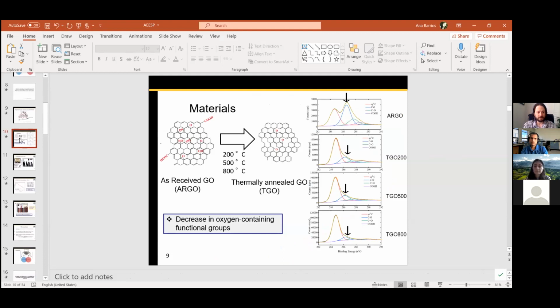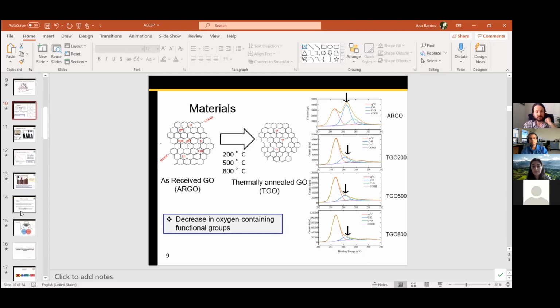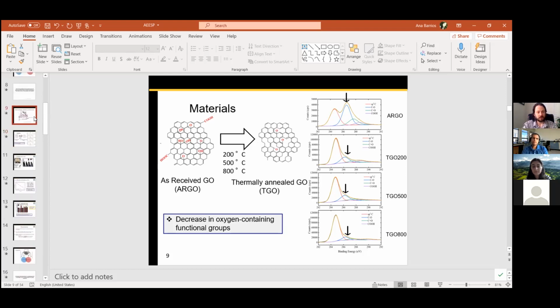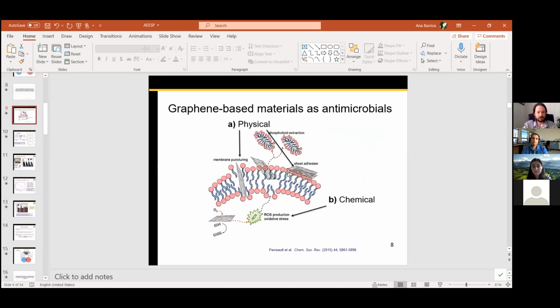The thermal annealing just basically helps us create materials with different surface chemistries. But really, when we look at the mechanism, we're dealing more with two types of mechanism. The first one that we saw was for the oxidized material, where we see a higher reactive oxygen species production. And so therefore we say that ARGO tends to have this type of mechanism happening within these bacteria-material interactions.